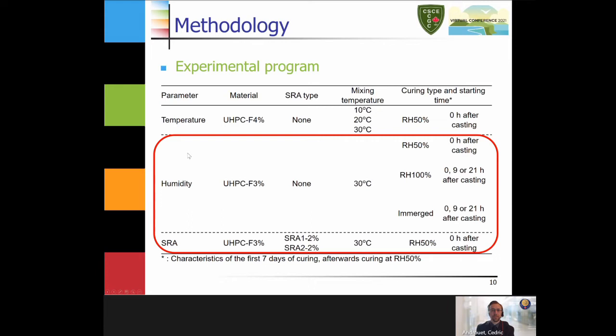For the experimental program, we studied the effects of temperature, humidity, and SRA. Because time is limited, we will focus on the humidity and SRA experimental program in this presentation, and I refer you to the paper we wrote for this conference for the effects of the temperature. So we have our reference mix with the mixing temperature at 30 degrees and a relative humidity of 50%. And we studied what happens if we have a relative humidity of 100% and what happens if we immerse completely the specimens in water, at different starting times, we're going to talk about that in a few seconds. And we studied as well the different shrinkage reducing admixtures at a dosage of 2%.